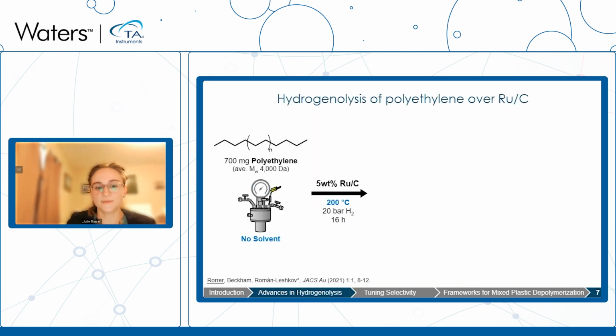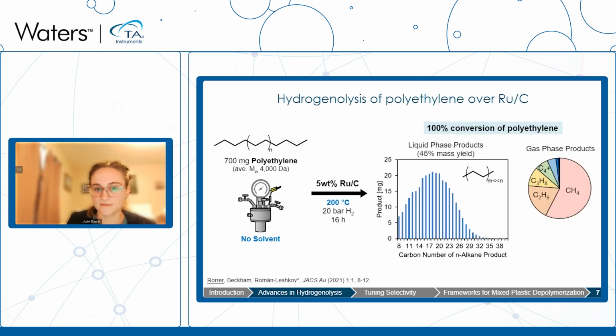So to start, a couple of years ago, we identified ruthenium-based catalysts as very active for the hydrogenolysis of polyethylene. The way that this process works is we have our model polyethylene substrate, we add it to this batch reactor in the absence of solvent. We add a 5% weight ruthenium on carbon catalyst and pressurize this vessel with hydrogen. And at 200 degrees C over 16 hours, what we are able to get is 100% conversion of our polyethylene to liquid and gaseous products.